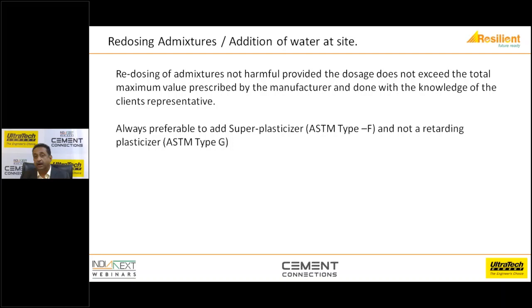What does the code say? Redosing of the admixture is not harmful, provided the admixture you're going to redose is still within the maximum permissible limits prescribed by the admixture supplier. And more importantly, the concurrence of the site personnel needs to be taken before you actually redose the admixture. It's always preferable to use superplasticizer rather than a retarding plasticizer, which can cause delays in setting.